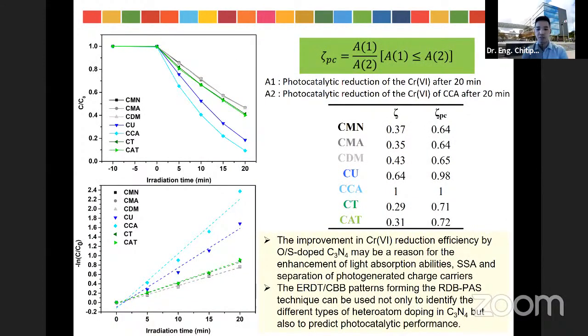Furthermore, we checked the photocatalytic activity of this sample by reduction of hexavalent chromium. It can be seen that the oxygen and sulfur-doped graphite carbon nitride show a higher photocatalytic efficiency than the undoped sample. So if you look at the slide, the black or gray color is the undoped sample, which has lower photocatalytic efficiency than the blue or dark blue color, which is the oxygen-doped sample, and the green color is the sulfur-doped sample. The improvement of the photocatalytic efficiency by doping with oxygen or sulfur may be attributed to the enhancement of the light absorbability in the visible light region and the improved separation of the charge carriers.